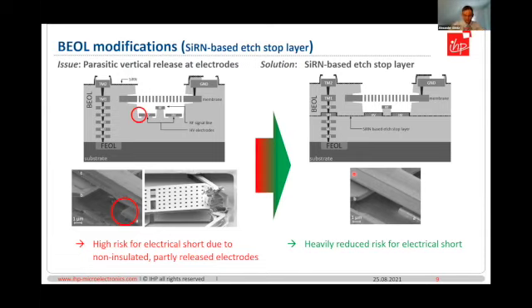The first issue I want to show is the parasitic vertical release at electrodes. Already shown here, and in a tilted SEM image you see this here. The electrodes are, or in this case, one electrode is already underetched. And in actuation, with a high actuation voltage, it can occur that we have a short. There's a high risk for an electrical short due to non-insulated, partly released electrodes.